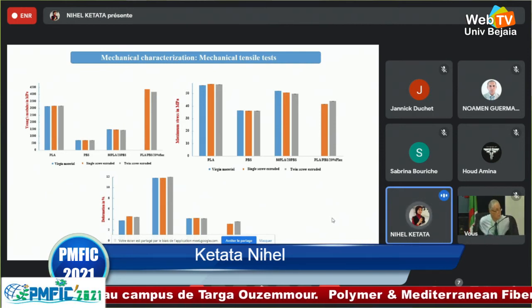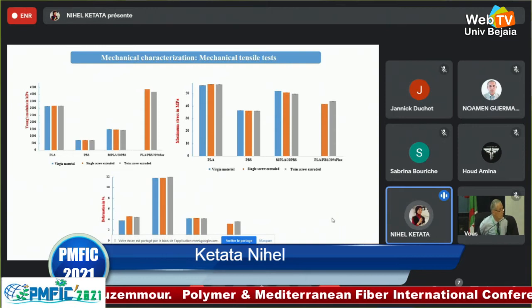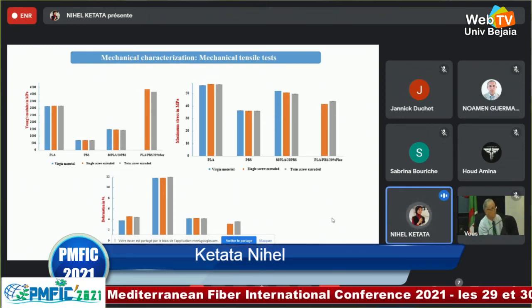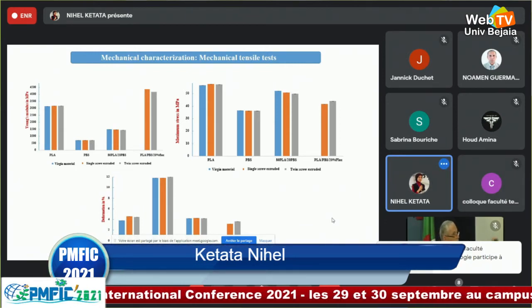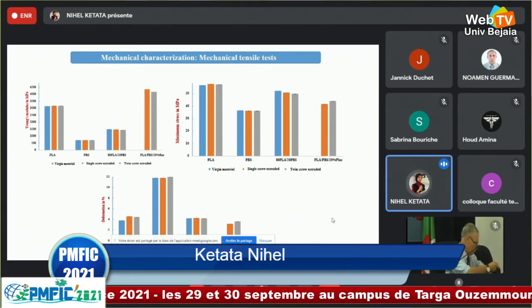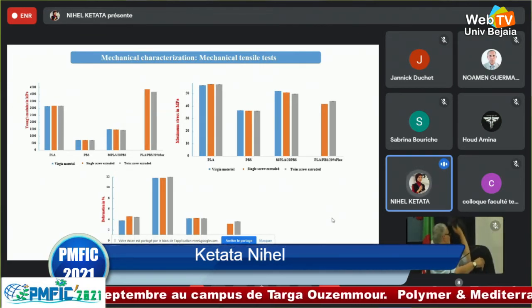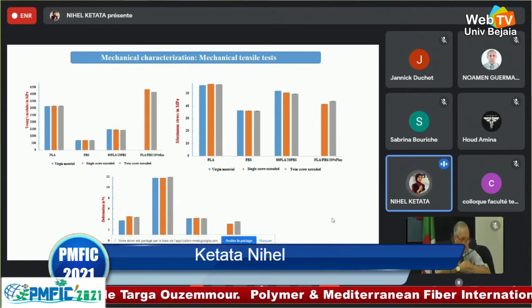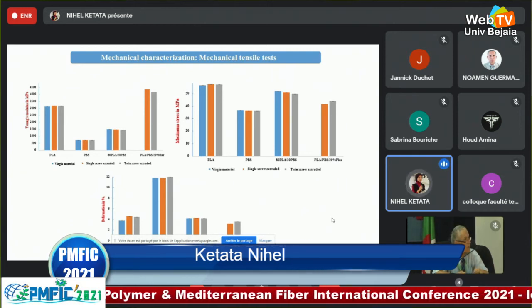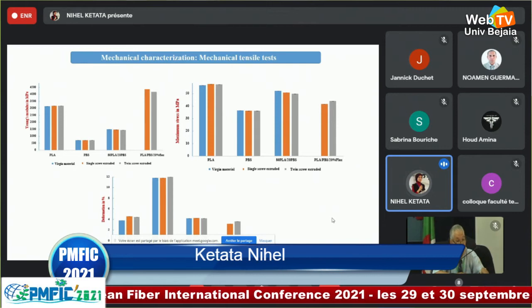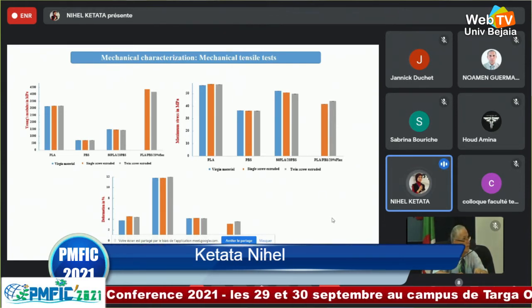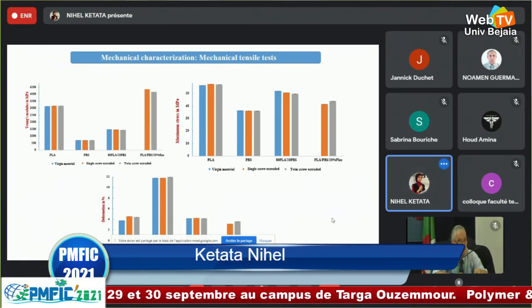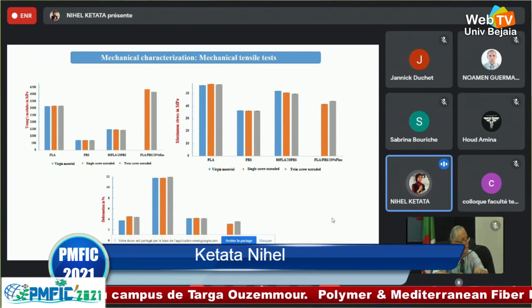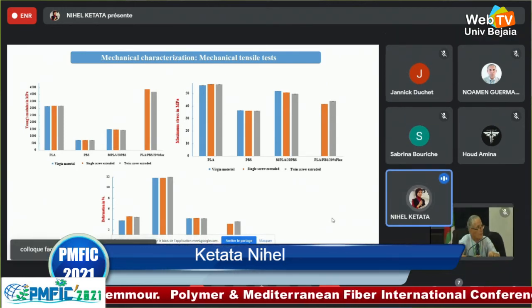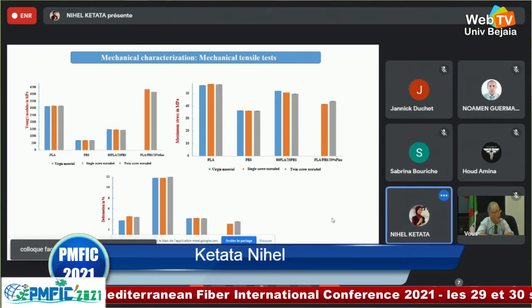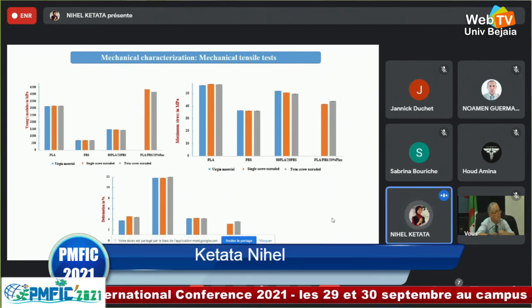For the deformation of this formulation, the tensile strain at break of PLA and PBS and their mixture are not significantly modified during single or twin extrusion. The strain at break of all flax reinforced composites is lower than PLA, PBS, and their mixture. The tensile strain at break for the composite reinforced with flax fiber is slightly increased in twin-screw extrusion compared to single-screw extrusion. So to conclude, we can say that the process, single-screw or twin-screw extrusion, has no significant effect on the matrix. On the other hand, it has a slight effect on the composite.